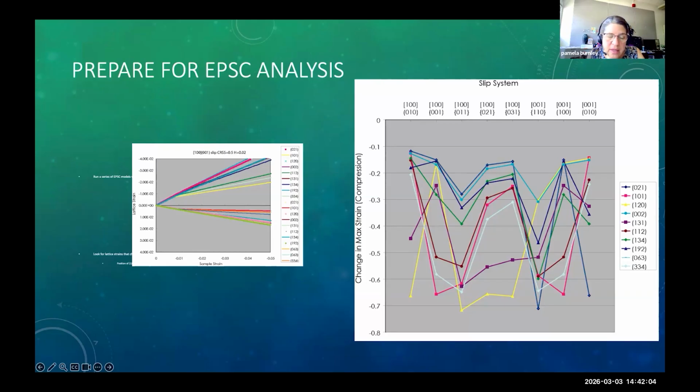And then I can look at the lattice planes that I can measure, and I can see, well, can I tell the difference between the operation of 100 slip on the 010 plane and the 100 slip on the 001 plane? And the answer is yes, you can. Because if you look at the 120, it's very different from the other ones, which are plotted clustering here.